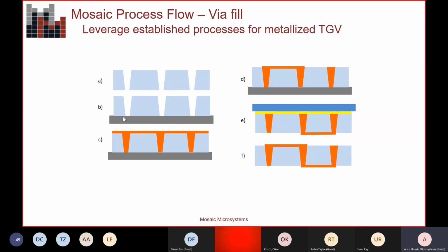Then you would take that via in step B and do, for example, a PVD adhesion and seed layer. Often it's titanium and copper, and then you do a bottom-up fill to fill those vias. Then from C to D, you might use that first metal layer and just pattern it as your first metal layer, or you CMP that off and deposit your first metal layer. Then step D could be a few steps where you put down your dielectric and then another metal layer, et cetera. So you do that front surface buildup, and then if you need to metallize the backside, you would probably use a more standard 3M or Brewer Science adhesive to bond to that top surface, debond the initial handle, and then do the backside metallization.